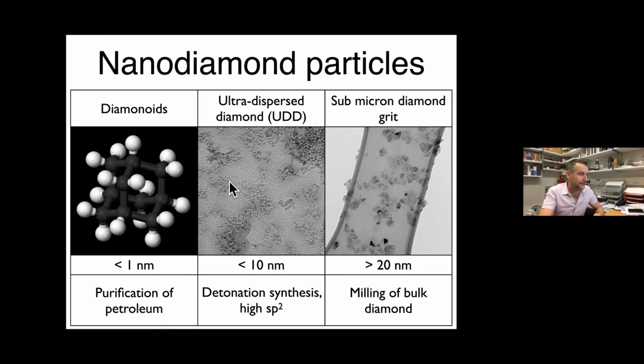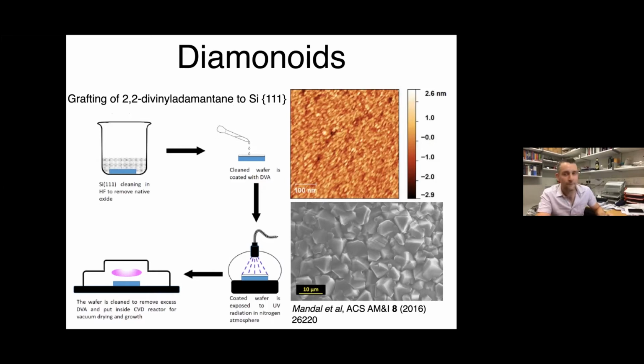Where is it? So some years ago, Suman and I spent way more time than we should have done trying to make them work as nucleation sites for diamond growth. So the story goes that adamantane, the smallest diamond, you would think, oh, cool, that must be the greatest diamond seed imaginable, is actually a terrible diamond seed. And the reason why is that it sublimes at about 250 or 280. So we got into a gang with some guys in Switzerland who basically attached some molecular tethers to it, so we could photo attach it to the silicon 111 face, which is super clever and everything, but honestly, it's really, really flawed, because the problem is the silicon always oxidizes. So you're trying to remove the oxide with HF, and then you're trying to quickly photo attach this molecule and then grow on it.